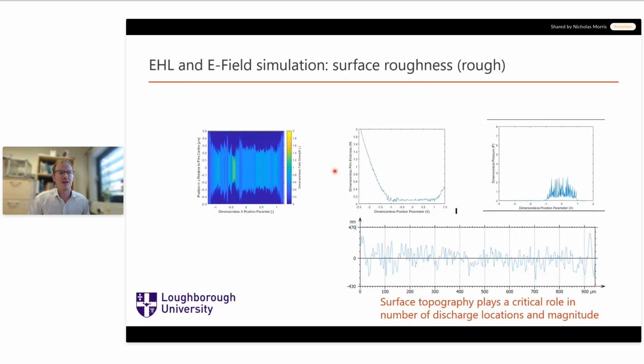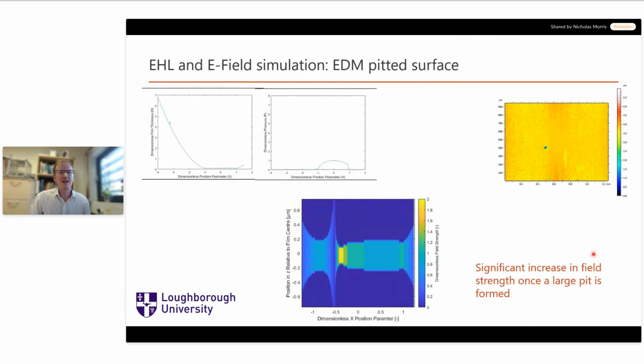the smooth surface. So we can see once the surface has been damaged through fluting, for example, which is similar to the roughness of the surface we see here, the field strength in the contact increases, and the propensity to further electrical damage then increases. The threshold that the common mode voltage has to achieve to cause ongoing electrical damage decreases, in other words. And that's up to 2 times, this model indicates. But it's more to show the order of magnitude that can change, rather than this being an exact representation of the contact. So we can also get more significant features that can occur.